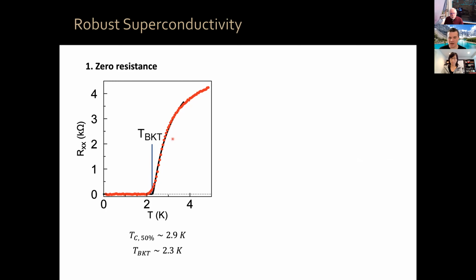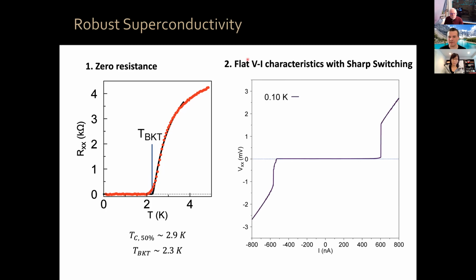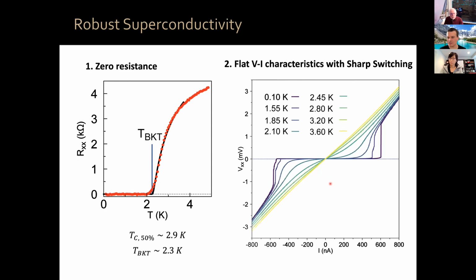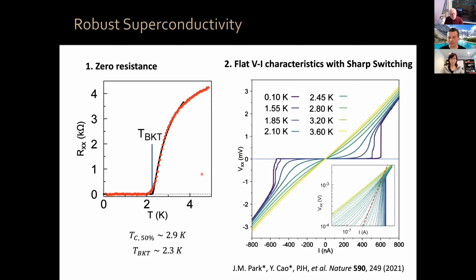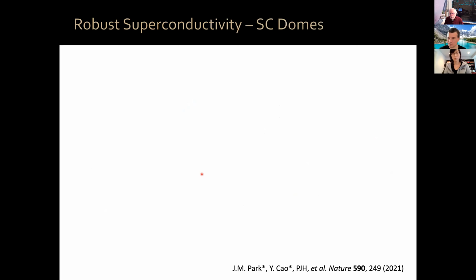Now, the next thing you want to do is see that this is truly a superconducting state, that you can run a finite current bias and there is zero voltage dissipation. So flat VI characteristics with a sharp switching. And indeed, you can see this is present. You can do temperature dependence. You can analyze this to extract your BKT transition, which coincides with what we extracted from the temperature dependence. Now, the system is also an electrically tunable superconductor, similar to the bilayer case.